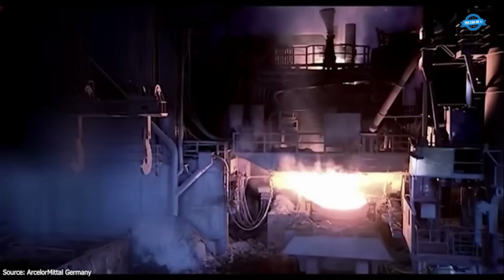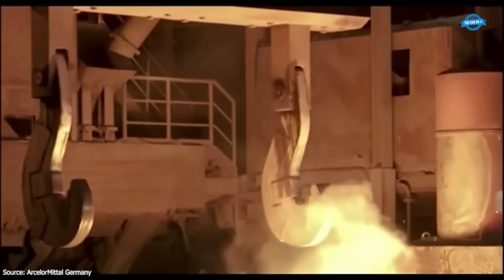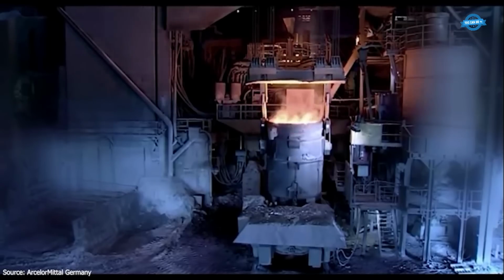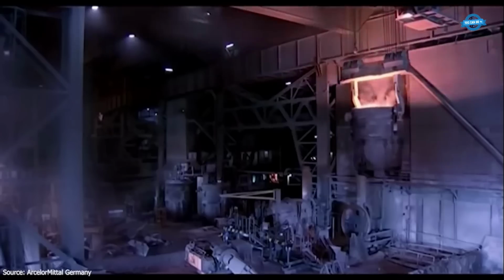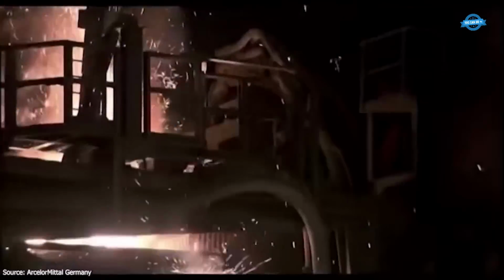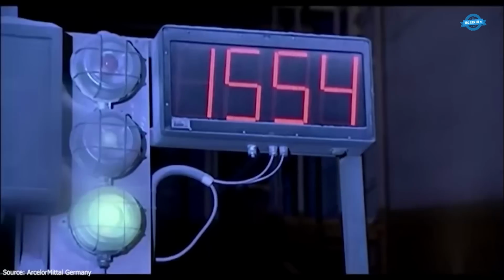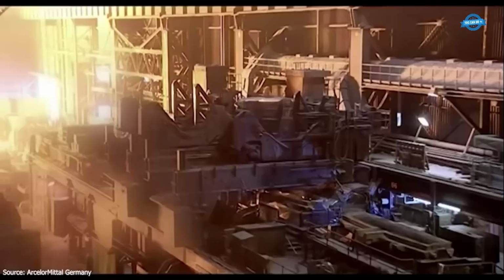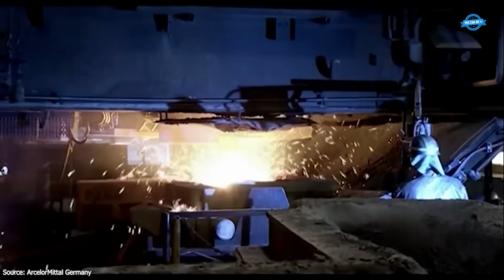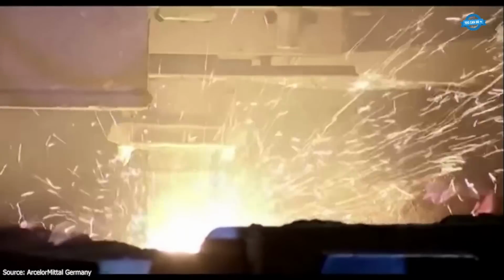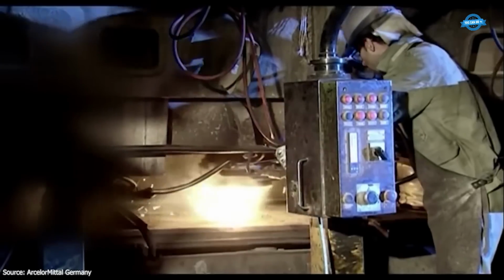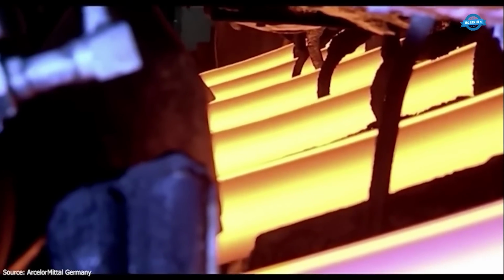Natural gas is heated to around 1,000 degrees Celsius, where it is split into carbon monoxide and hydrogen gases. These gases reduce iron oxide into nearly pure metallic iron, known as sponge iron, without melting the ore. This method significantly lowers energy consumption and carbon dioxide emissions compared to conventional methods. The produced sponge iron, along with steel scrap, is then melted in the EAF.